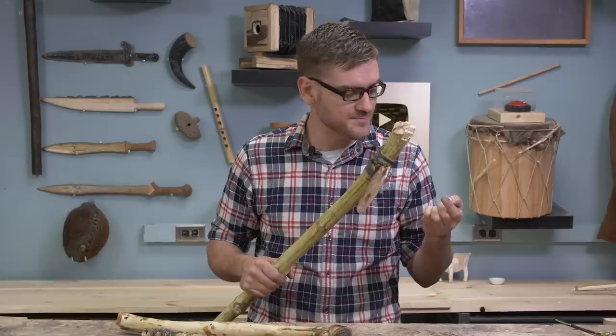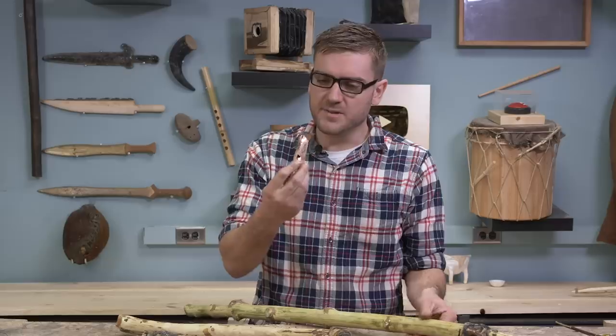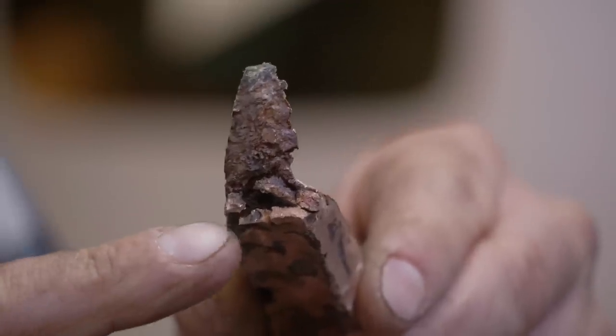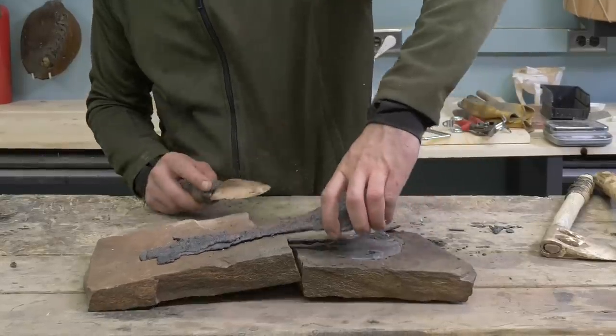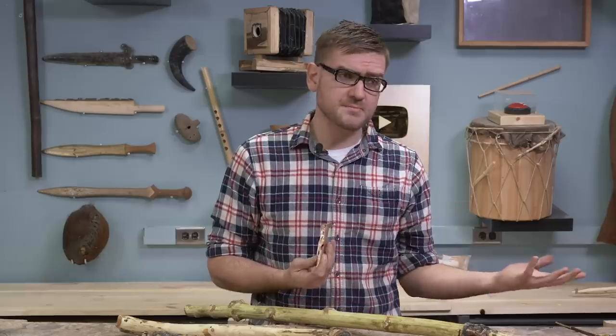It did break, but not where you expected, in the back. This is just on the backswing, it hit the ground and bent and broke this part. If you look inside, there clearly was some sort of air pocket that got trapped, made it a little bit weaker. There's some obvious flaws with the stone mold that I haven't really figured out. There's also a lot of work, and that was just one side of a mold. Usually they would do two, they fit together.